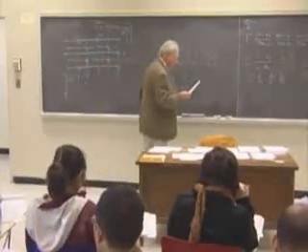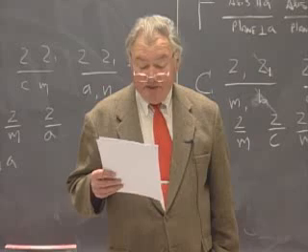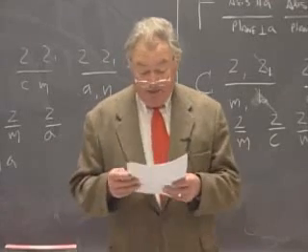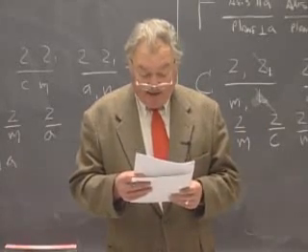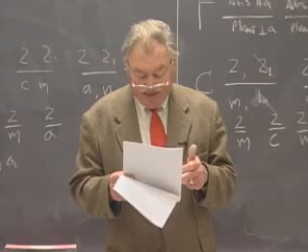And then when you come to monoclinic, the Schoenflies symbol has the marvelous property that it is independent of the orientation and labeling of axes. It depends only on the point group that the crystal has. For monoclinic, either C2 or Cs, that's a mirror plane, or C2h, that's 2 over a horizontal mirror plane. But the labels can still change depending on whether in the first setting either A, B, or the diagonal of the oblique net has to be labeled A and C. So at the top of the column, you see the permutation of the 2 symbols, A and B, or B and A. And again, the change is significant. Number 8, as indicated in the left-hand column, can be BM or AM.